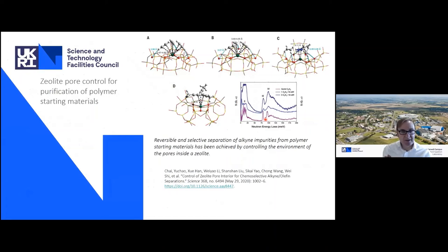This is a nice example from Sihai Yang's group in Manchester, which is trying to develop materials to more efficiently reduce the energy and environmental cost of producing materials, in this case polymers. This is to do with alkenes, propene, ethylene, that need to be separated from alkynes before they can be converted into polymers. Now, typically zeolites are quite inefficient at this process, but the group at Manchester realized that by adding nickel, which is the green atom here, these are neutron structures determined by powder diffraction, you can actually see that the alkenes are binding selectively at the nickel 2+ site.